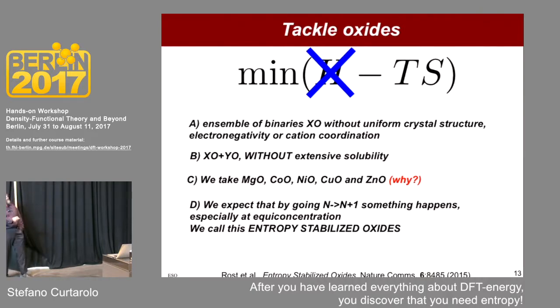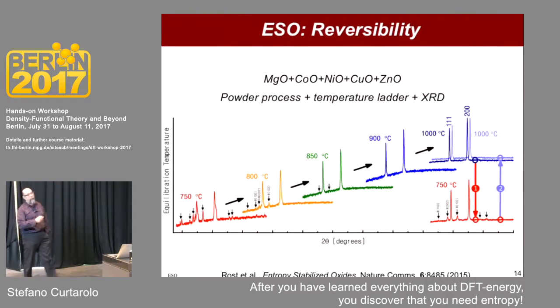If you take, do you see, you have 5. If you take any 4 of those, they don't mix. If you add any combination of 4, you can leave out zinc, you can leave out nickel, whatever you want to leave out. Any 4 combination of these 5, which is binomial 5 choose 4, is not going to mix. When you have 5, they will mix. So this is what we find.